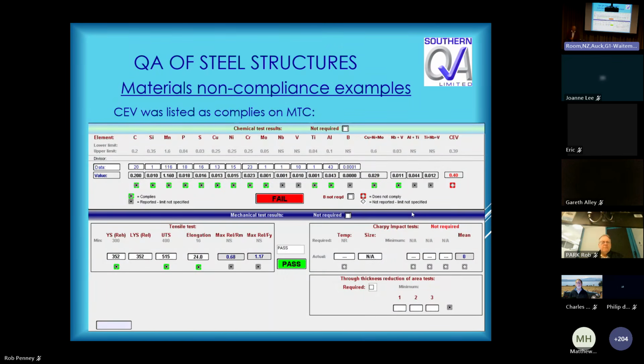Here's another one, the carbon equivalent value. When you're welding, the carbon equivalent value is quite important. The carbon equivalent value on this particular material certificate, I hope everybody can see that okay, might be on the back, might be a bit tricky, but you'll see there's a big red fail here. This is off our database, where you can upload from an Excel sheet or manually input the values on the material test certificate, and it spits out whether the chemical and mechanical values pass. In this case, you can see the CEV limit is 0.39, and the CEV for this particular set of chemical values is 0.40.